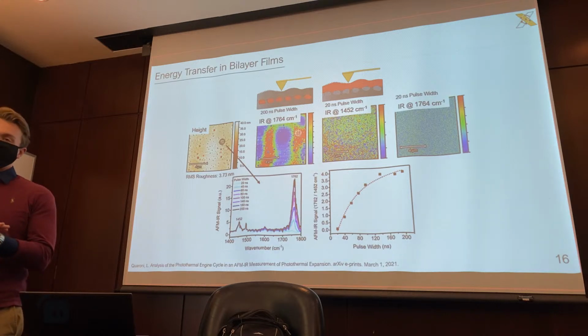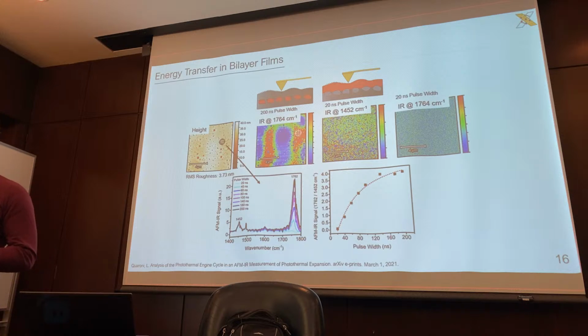Right. So that interface between the silicon and your polymer is going to act as kind of a heat sink as well. So you are going to lose some efficiency in signal generation that way, the more interfaces that you have. Yeah. So is that why bulk samples burned up? Because there's a localization of heat and you increase the laser power to try to compensate and then it was too powerful for the material?